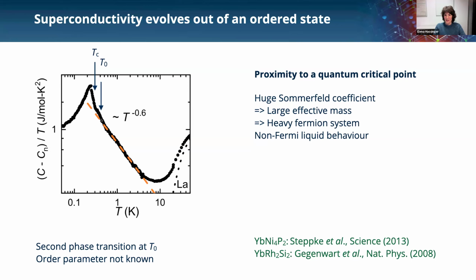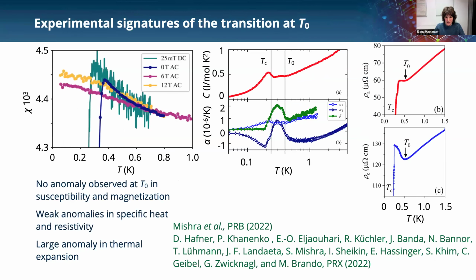So there are signs that this system is close to a quantum critical point, which is the low transition temperature, but also the strong increase of the specific heat, C/T, as we decrease temperature with this strange power law, and a very large value of the effective mass here. So we don't know, there's no microscopic measurement yet of the order parameter, or at least at this temperature, T0, you will see later.